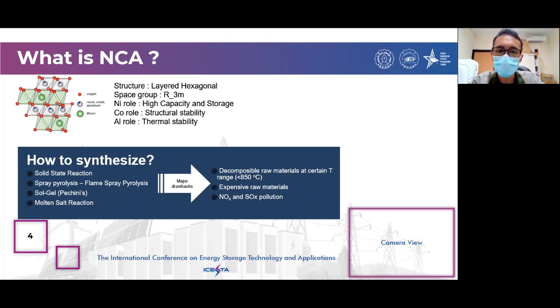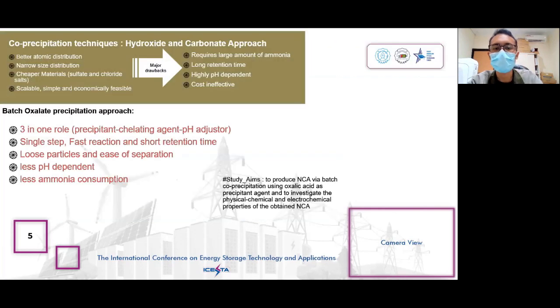Several methods that can be used to synthesize NCA materials include solid-state reaction, spray pyrolysis, flame spray pyrolysis, sol-gel, and molten salt reaction, which have drawbacks including decomposable raw material at certain temperature ranges, expensive raw material, and NOx and SOx pollution. Oxalate precipitation is the most effective method because it has advantages including 3-in-1 roll, single step, fast reaction and short retention time, loose particles and ease of separation, less pH dependence, and less ammonia consumption when compared to using carbonate and hydroxide, which have many disadvantages as above.